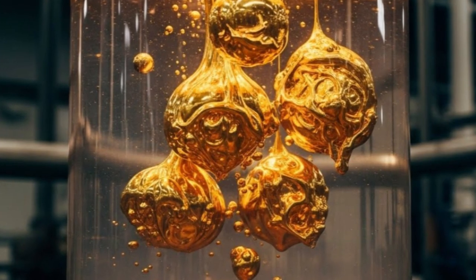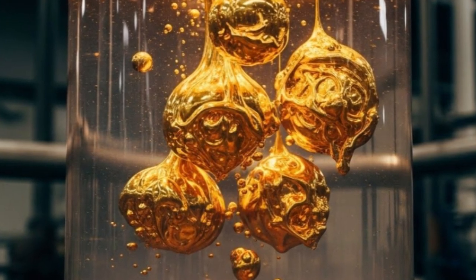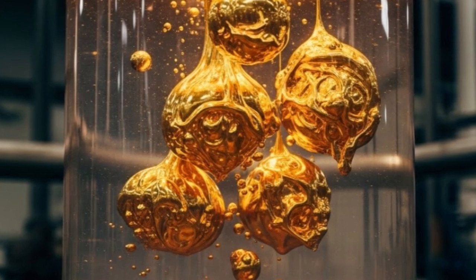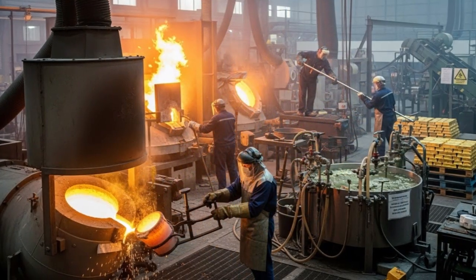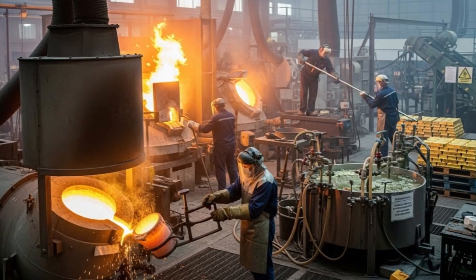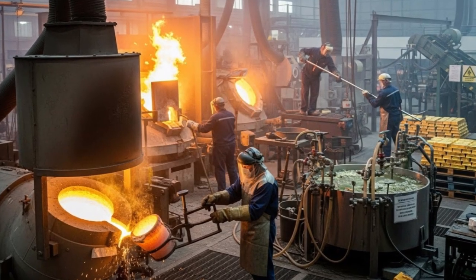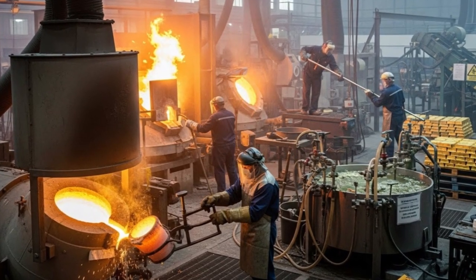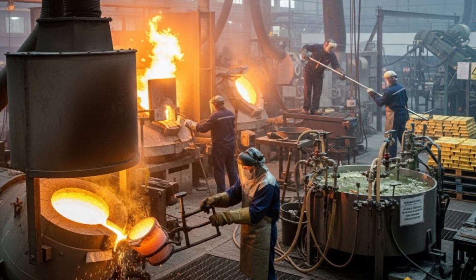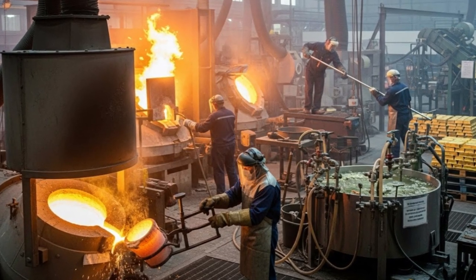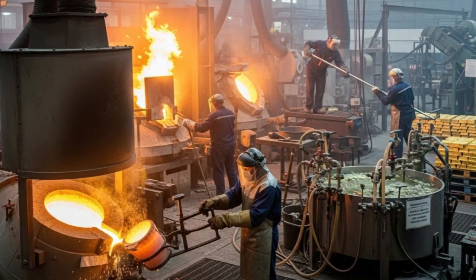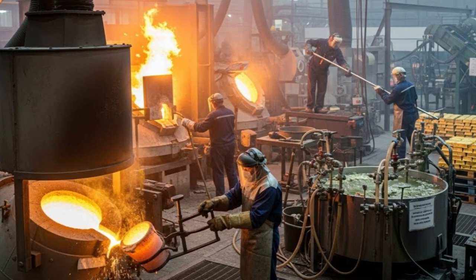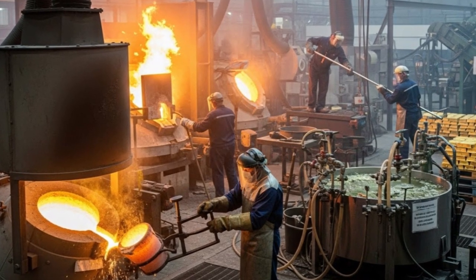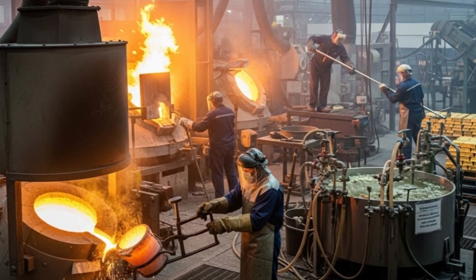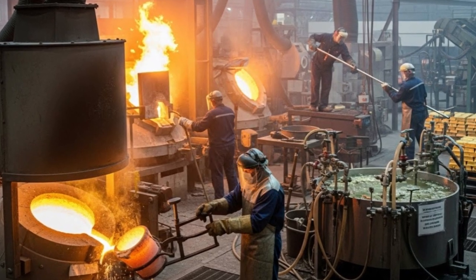Here, heat and chemical treatments are used to strip the gold from the carbon, producing a much smaller volume of highly concentrated gold solution. At this scale, precision is everything. A minor miscalculation, incorrect flow rate, temperature, or timing can result in millions of dollars worth of gold being lost. But when executed correctly, this step delivers gold exactly where engineers want it, ready for final recovery.